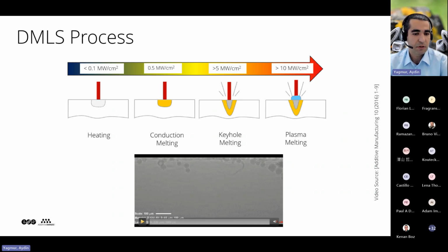Let's have a quick look at a video from this source, where we can observe the formation of the keyhole during this dynamic process. Between the red dashed line and blue dashed line, what we see is the molten metal. And within the blue line, we see so-called keyhole melting. In this area, we have a laser beam and metal vapor. And this area can also create so-called spatters, which I will give some more details on in the coming slides.